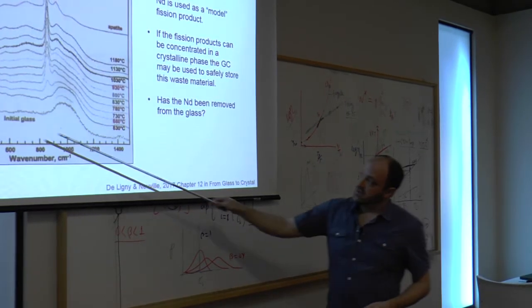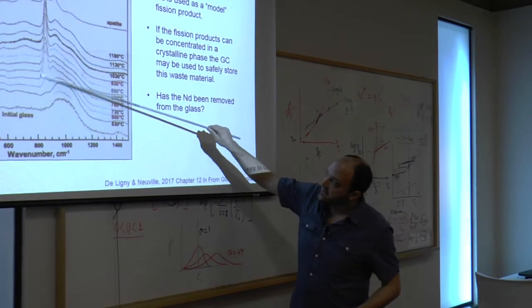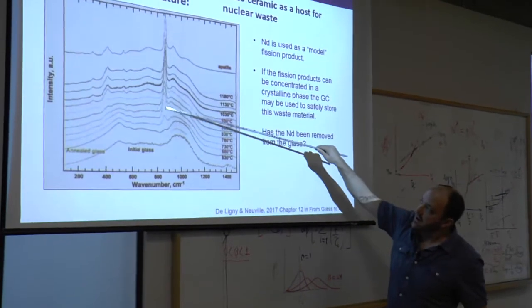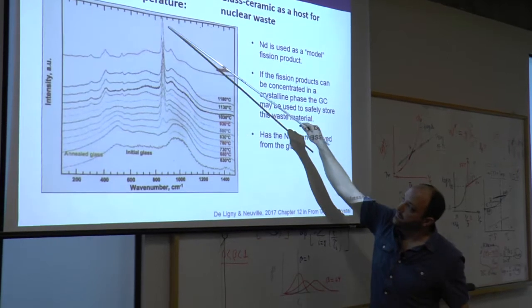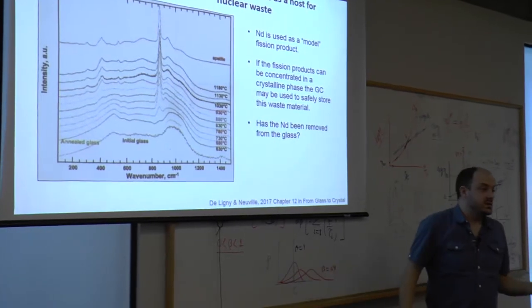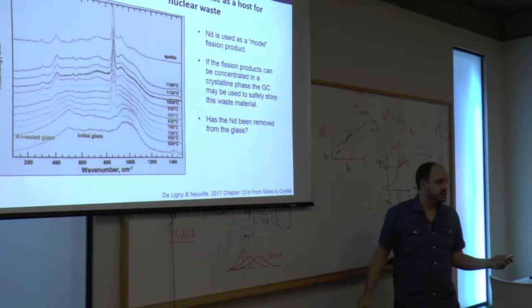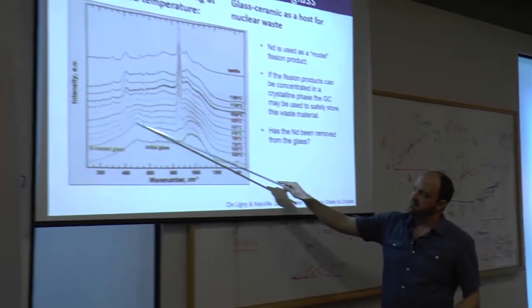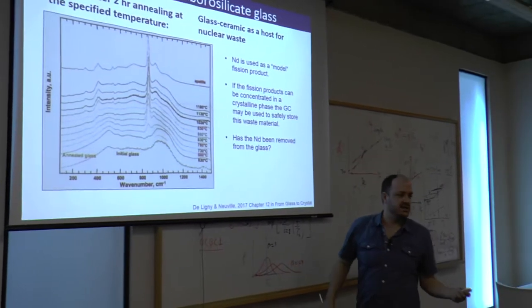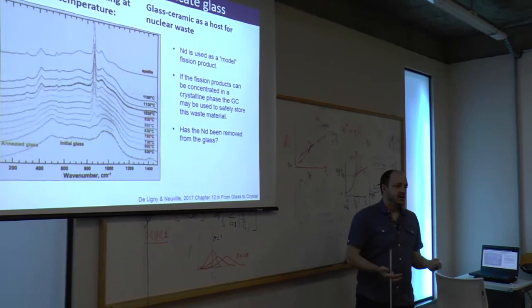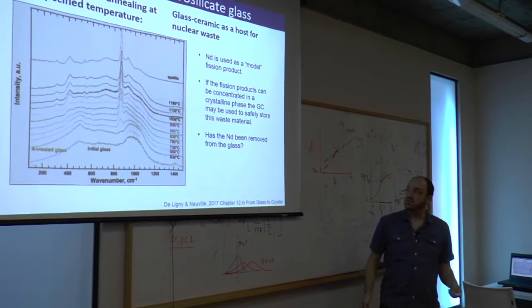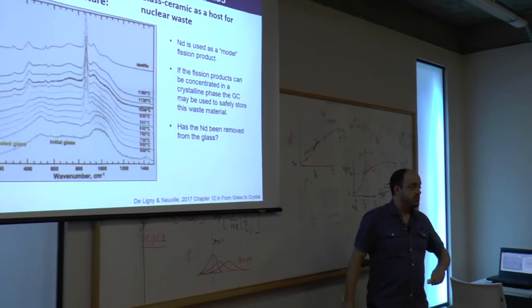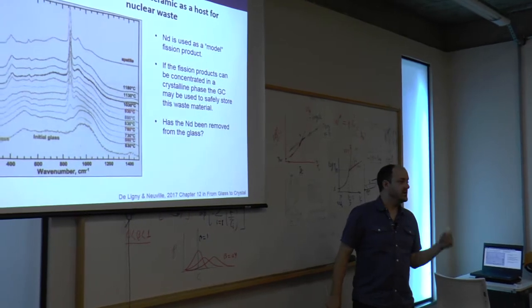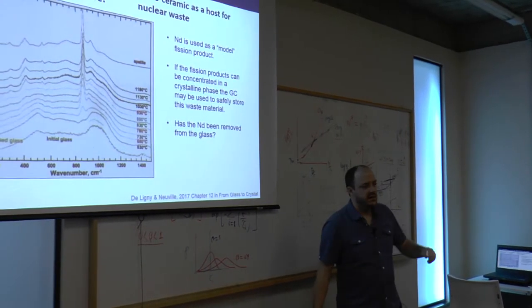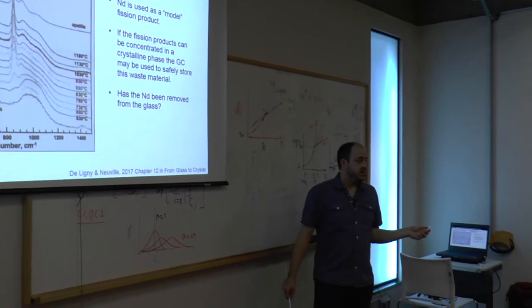You can see that the spectra are quite complicated. You can see also that as you increase the temperature, there's this sharp growth of this peak here, and there are some other sharp features. These are what you would expect of those crystalline spectra, and we saw a few examples. But you also get very broad bands related to the glass. So we have to unmix the different contributions to the spectra from the mineral. And we know that minerals have a really intense Raman signal. You can get a really good spectrum of a mineral in 10, 15 seconds under optimal conditions. But for a glass, you need much longer to get the same